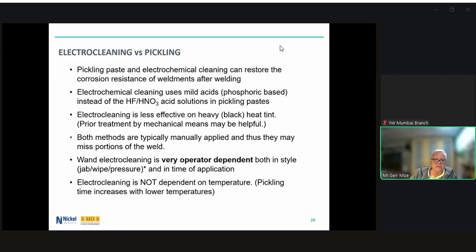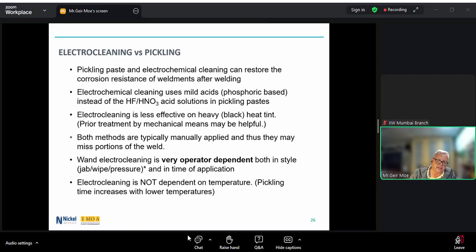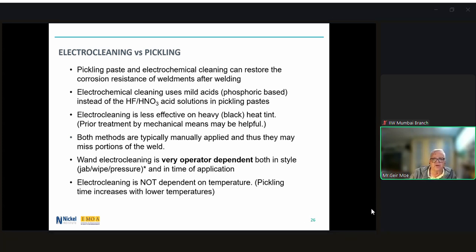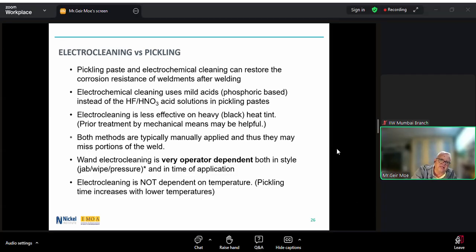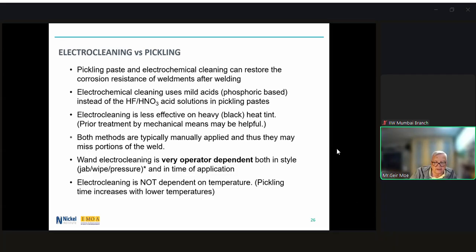With pickling, time increases with lower temperatures, because as we know, chemical activity doubles with every 10-degree centigrade increase in temperature. So the time for pickling would take much longer if you were doing the pickling at 10 degrees C versus say at 20 degrees C, or even say at 30 degrees C.